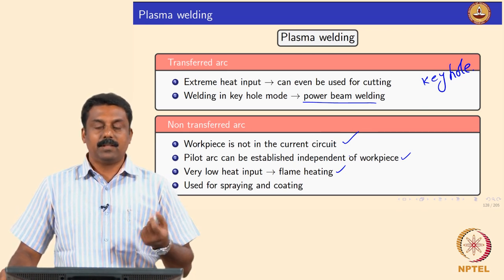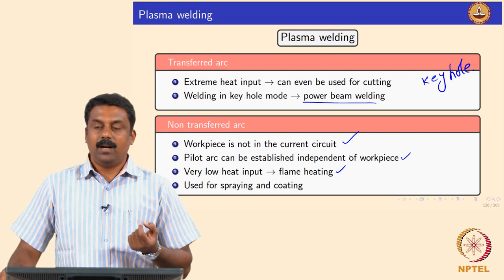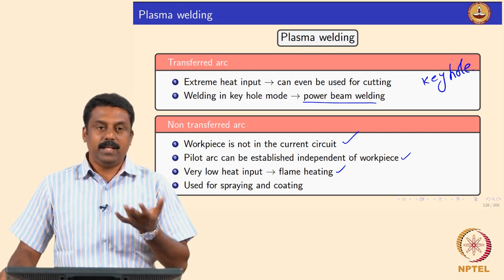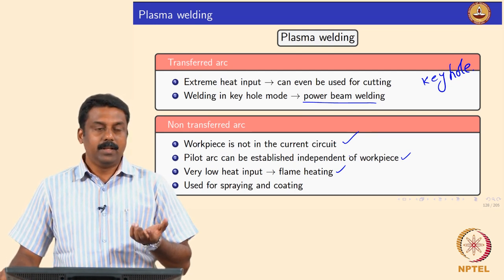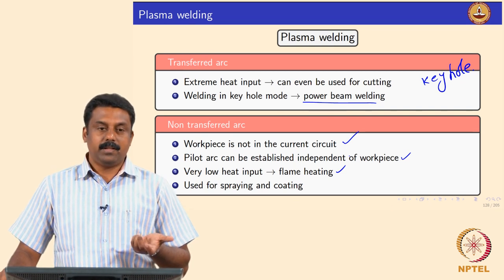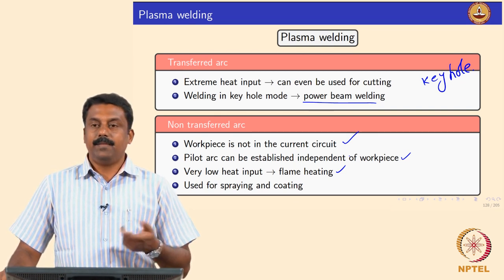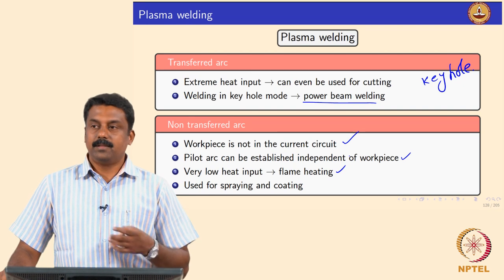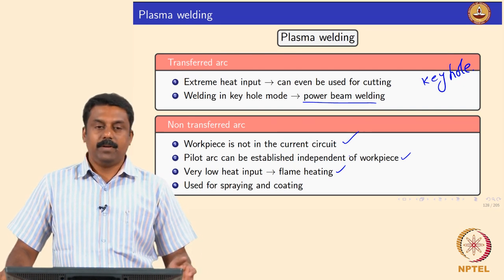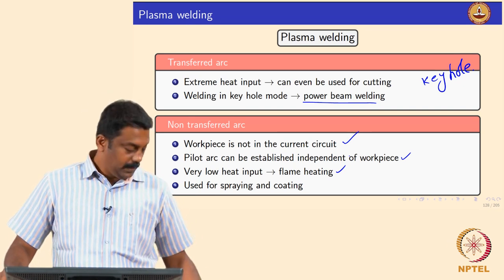And generally, we use a slightly larger diameter tungsten electrode, because the energy density at the tip increases tremendously because of the arc constriction. So the diameter of the tungsten electrode we use for plasma is much larger than that used for GTAW. Good.